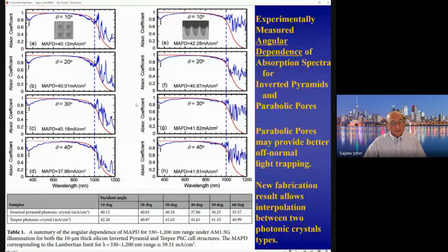We've also done detailed experimental studies at other angles of incidence in both the inverted pyramid structure as well as the parabolic pore structure shown on the right, at angles of incidence ranging from 10 degrees up to about 60 degrees. And this shows the change in the absorption spectrum as you go more and more off normal. The absorption remains pretty good in the inverted pyramid structures until you reach about 40 degrees off normal, where it starts to get smaller. We're down to about 38 milliamps here.